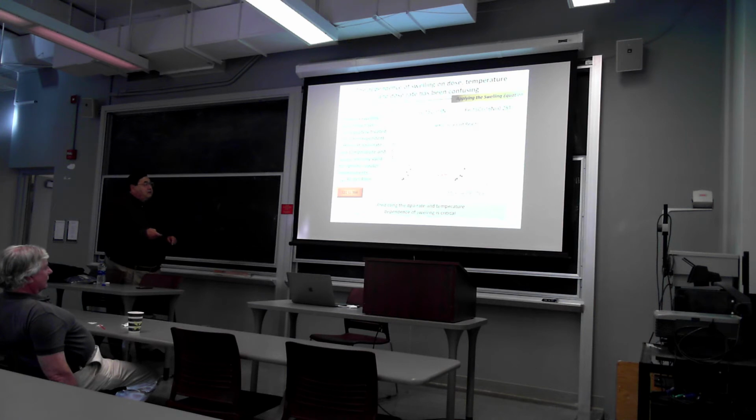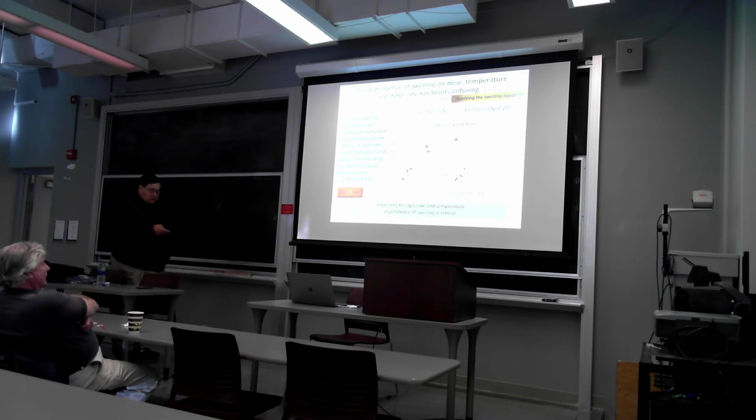So here we go. That's what you get. So this is a modified 321 stainless steel swelling equation that's been modified to look like iron 15 chrome nickel. Okay, and here's how we are able to explain this data which had never been explained before, even though it's been in the literature for many years. Okay, I'm going to give you one other example. I have half a dozen other examples, but this one I like.